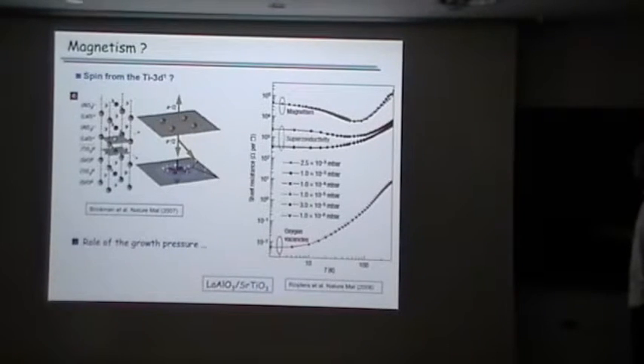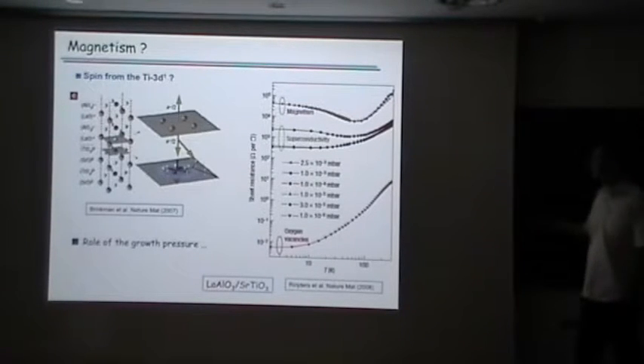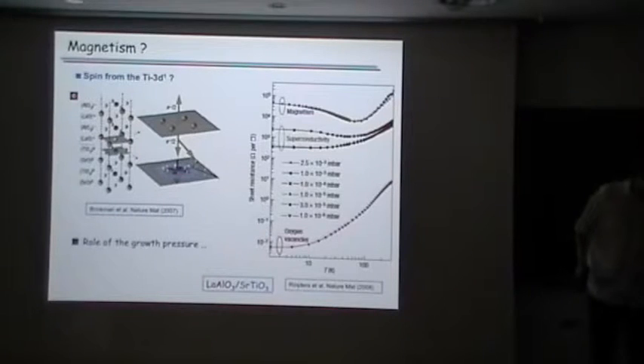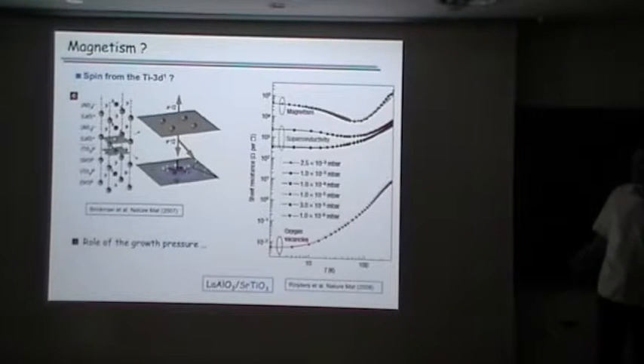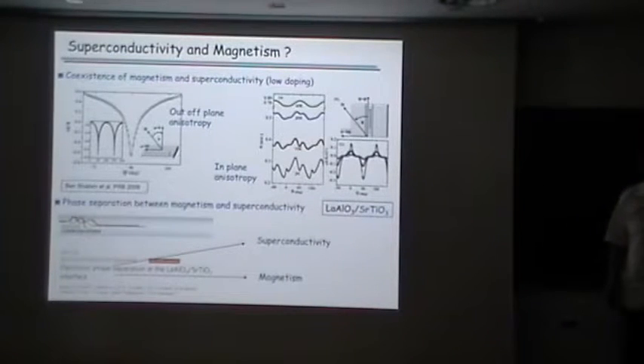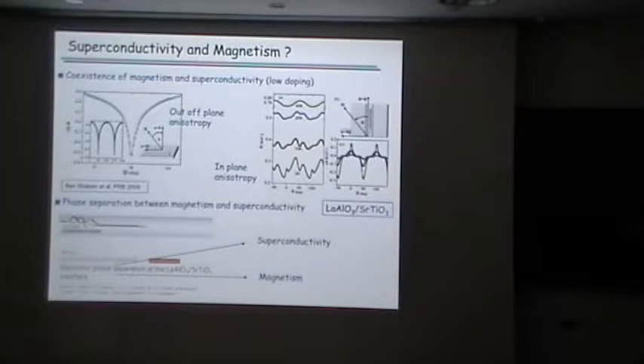I think this is where, for sure, we are in the range where there is a gas at the interface which is very confined. In the case where you can find magnetism, it's a very low number of carriers, usually rather high resistivity, and I'm not sure these kinds of results have been completely reproduced, I mean the result from Brinkman, maybe because in this case, this is not the best way to get clean interfaces. There are also rumors or papers about coexistence of magnetism and superconductivity.